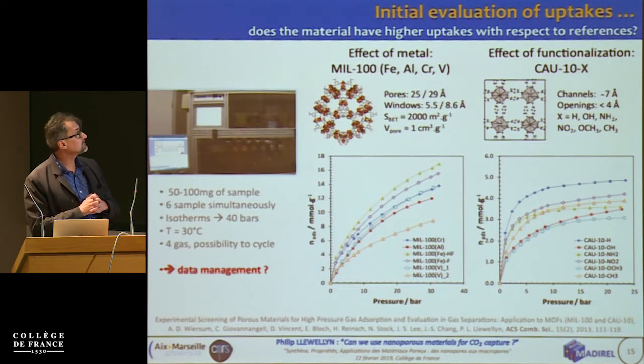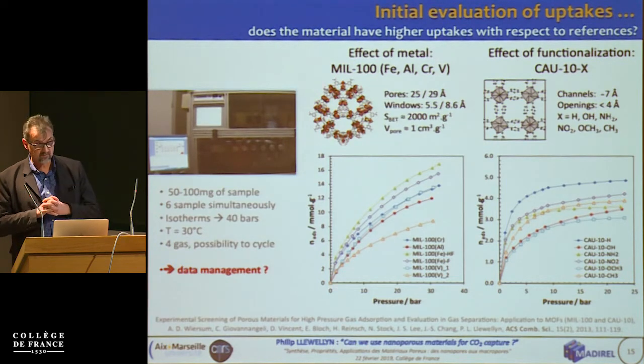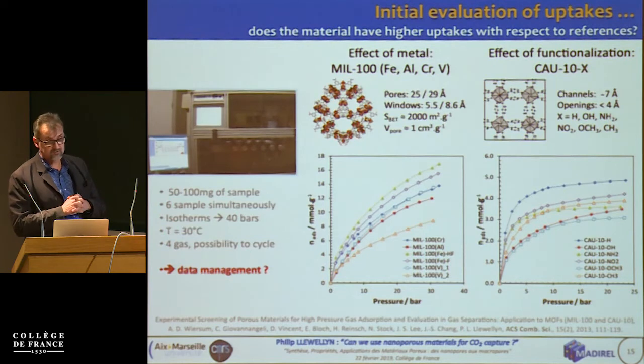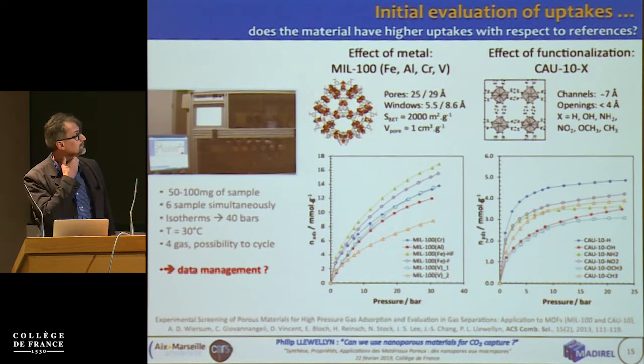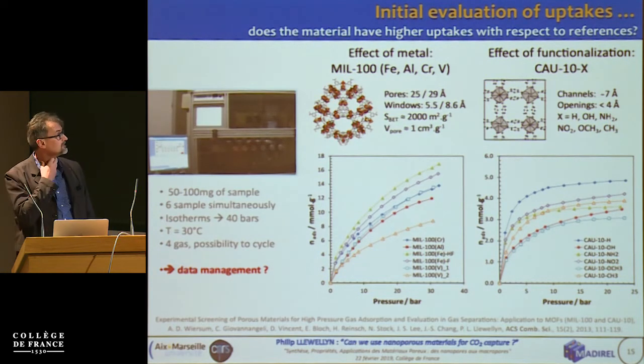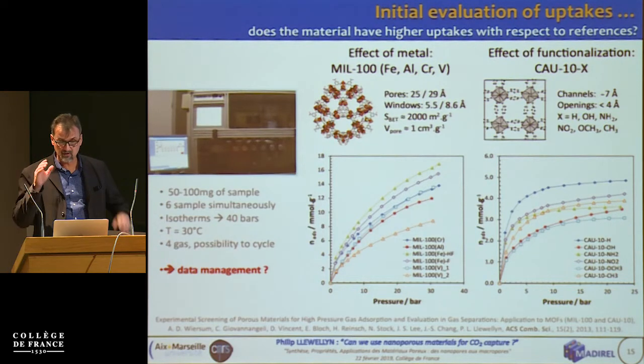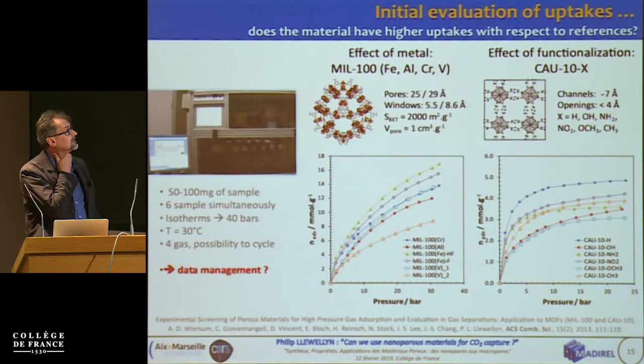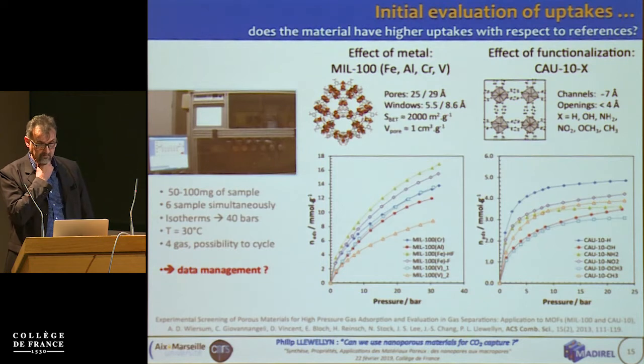And we've got a program set up that we can look at isotherms up to pretty decent pressure at different temperatures, but we stay mostly at 25 to 30 degrees. But also we can change the gases, and we can look at 4 different gases sequentially, which is really nice. And it's possible to cycle, so we can do a lot of things already with quite a simple system that we built in the lab.